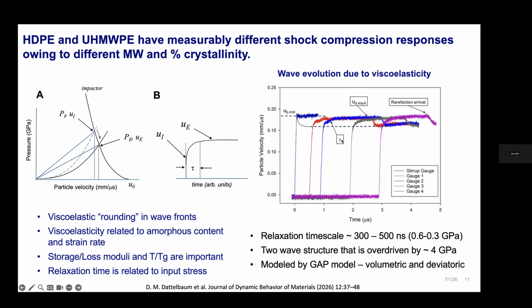So the relaxation has a time associated with it, and when you look at this in a pressure particle velocity plane, you basically shock up to an instantaneous state, an instantaneous Hugoniot state, and then you relax down to higher particle velocity in the equilibrium state. So just from the wave profile, we get a measure of the instantaneous state, the equilibrium state, and the relaxation time associated with that relaxation process.